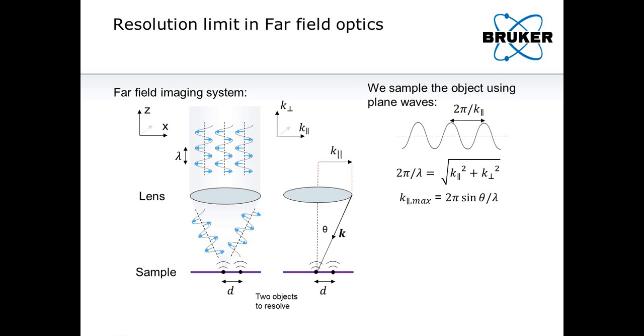From the dispersion relationship for light, you can see that the maximum K parallel that you can achieve is going to be 2 pi sine theta over lambda. Now, that's the highest spatial frequency that you can use to sample your sample surface. So the smallest separation distance d that you can have between the two objects you're trying to resolve is going to be limited by this largest spatial frequency that you can achieve.